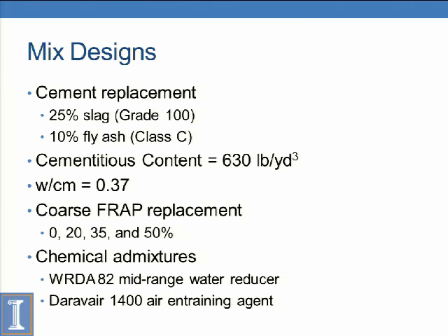Ternary mixes are, I shouldn't say new, but they're gaining more ground in terms of use. So the tollway is definitely interested in using high proportions of sustainable materials because slag and fly ash, both being byproducts, are sustainable materials. Now the cementitious content we used was 630, which is a little bit high for a regular pavement. Usually a pavement will have maybe 575 pounds per cubic yard, but we wanted to have enough cementitious content to have good strength gain since we knew the strength properties would probably be decreasing.